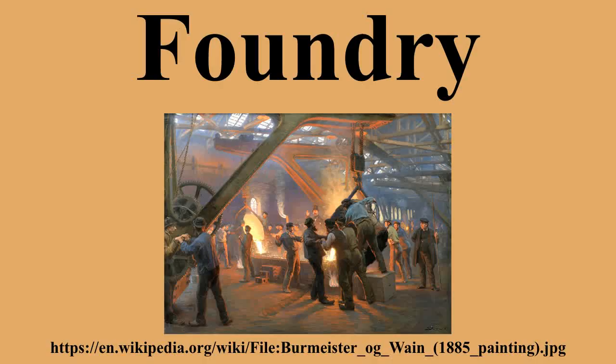It forms as a result of material reactions from water vapor or machine lubricants. If the hydrogen concentration in the melt is too high, the resulting casting will be porous. The hydrogen will exit the molten solution, leaving minuscule air pockets as the metal cools and solidifies. Porosity often seriously deteriorates the mechanical properties of the metal.